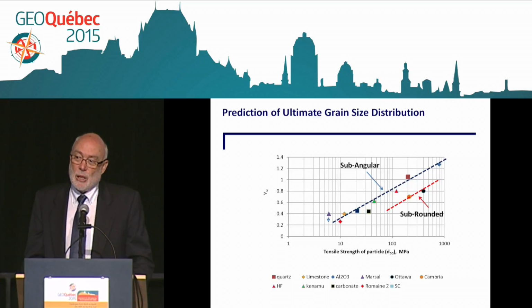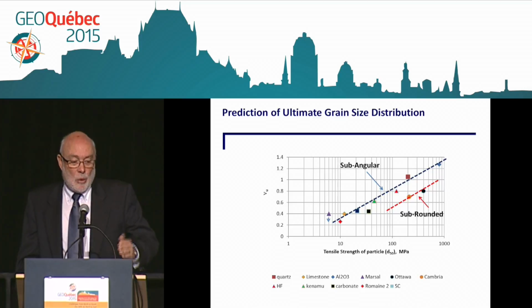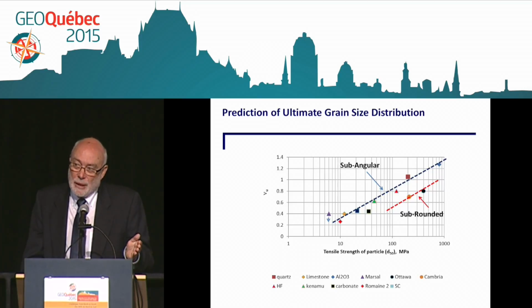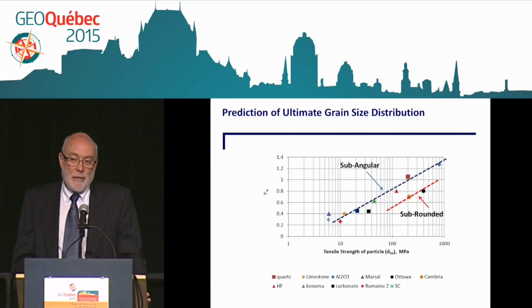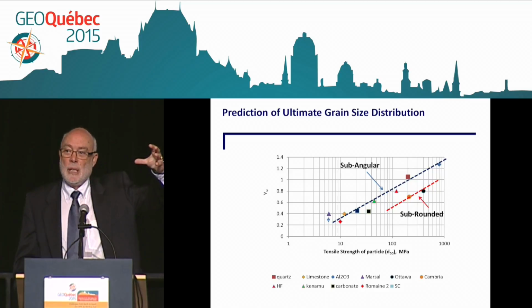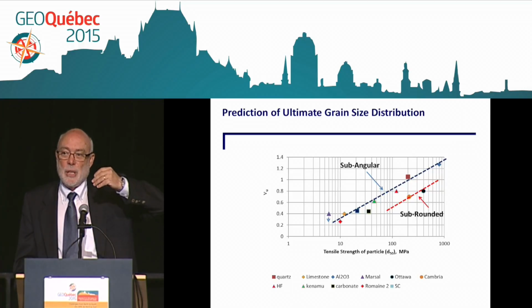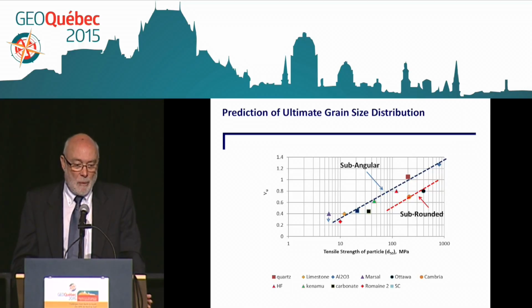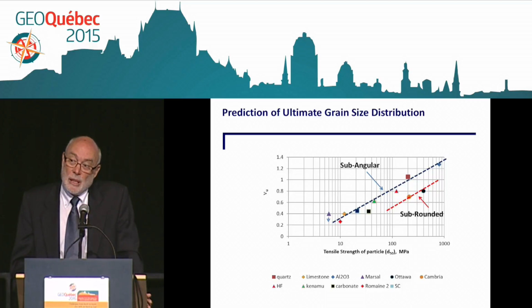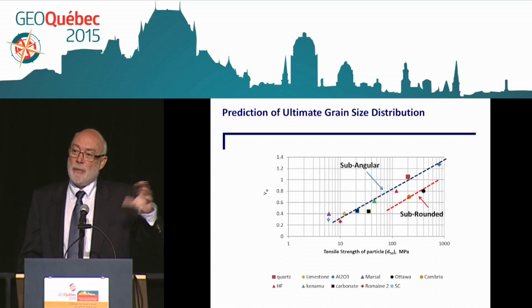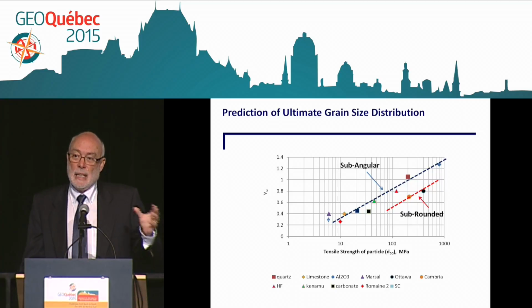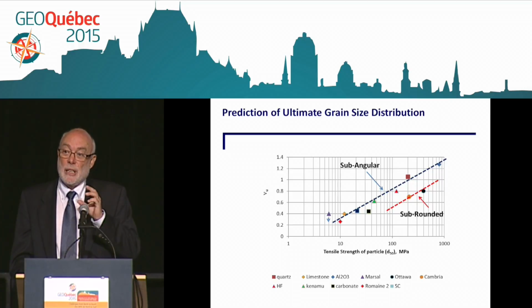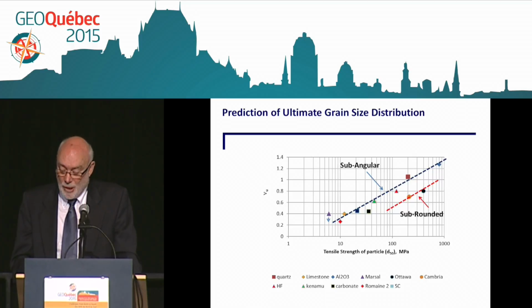the steeper would be the slope, so that means less crushing or fragmentation. But the weaker the particle, the lower is the value of that angle, and therefore it's flatter, and we get much more crushing and fragmentation, and we're going to generate more fines. We also have seen that there is a difference between subangular particles and sub-rounded particles. Now in dams we have both. Subangular would be the shells when we have clean gravels in transitions or filter zones, clean sands and rounded sand, we're going to have to work with the sub-rounded particles.